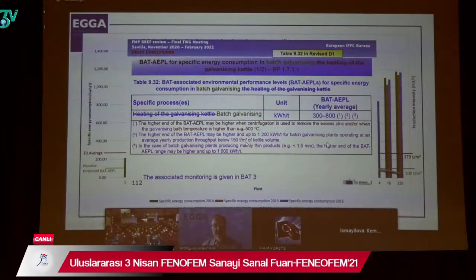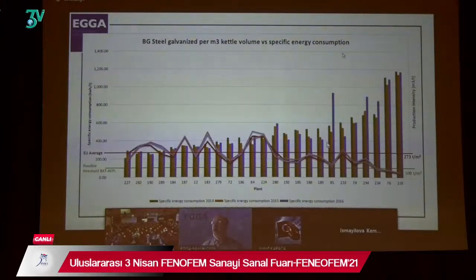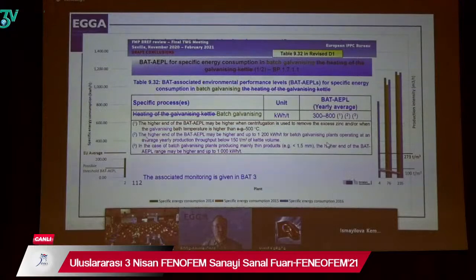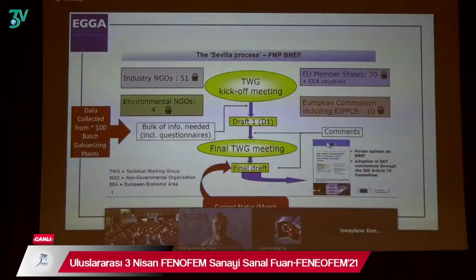So these are small details, but they're very important, because if you are a plant that is at the high end, above 800, you could have a problem with your permitting authority. So these notes, like our note number 2 here, is very important to recognise that depending on your production level, you can have the best energy efficiency measures in the plant, but you would never get below 800 because your production level may be low. Okay? Again, it's just an example of the type of work that we had to do with the European Commission at the end of this process.